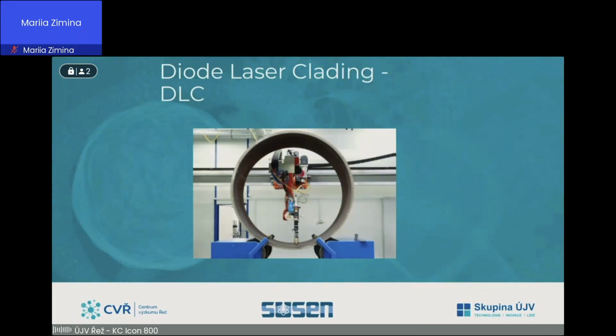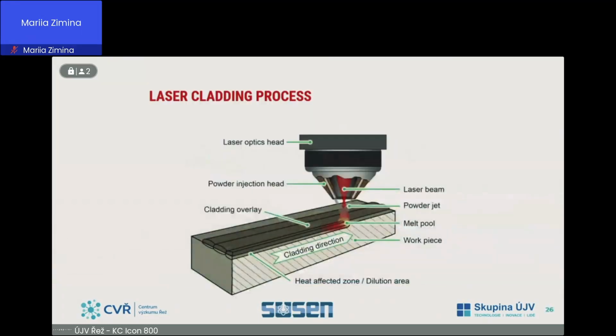Almost all types of laser can be used for cladding, but diode lasers offer many advantages thanks to their relatively low cost of purchase and operation. The main potential advantages of diode laser cladding are: it can be used out of position, whereas conventional cladding is performed in the downhand horizontal position only. Significantly smaller amounts of cladding powder are required, which could lead to substantial cost savings over conventional processes.